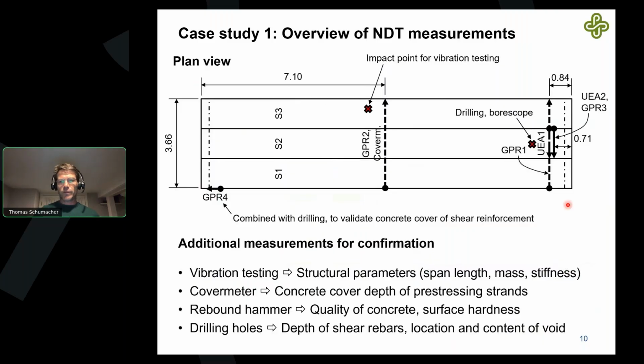This is a plan view of the bridge. You can see the 3 slabs here. You can see the different measurements we took. So we have UEA, that stands for ultrasonic echo array. So we did some ultrasonic measurements. For imaging purposes, we have GPR, ground penetrating radar. We did some impacting to do some vibration testing. And we also used a cover meter to measure the cover thickness of the pre-stressing strands at the bottom.